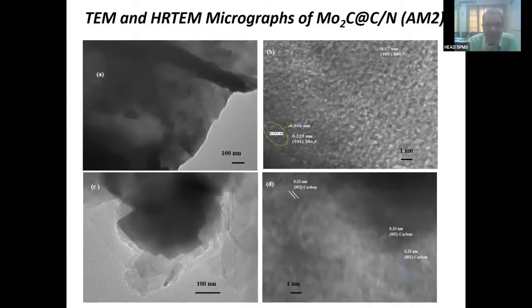Okay, the second part I want to illustrate in this microstructure is the embedded carbide inside the graphitic sheet. The dark structures are the embedded carbides. And once you go to the higher magnification micrograph, we have confirmed that later. So within the graphitic sheet, the carbide is embedded, just like a sandwich. Sandwich, you must have eaten, embedded. This is a very fascinating microstructure. First of all, because of the presence of carbon, the material becomes highly stable. Second, it is a sandwich, so it will provide very good properties whenever we are talking about the property of the material. So these structural features become very, very important.